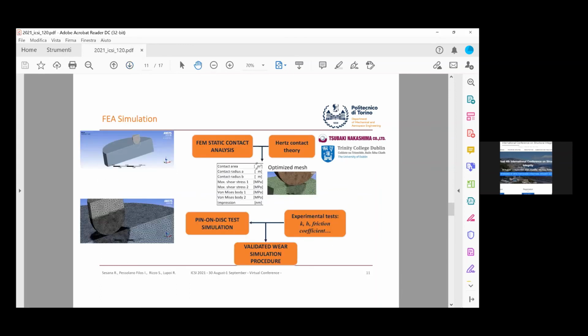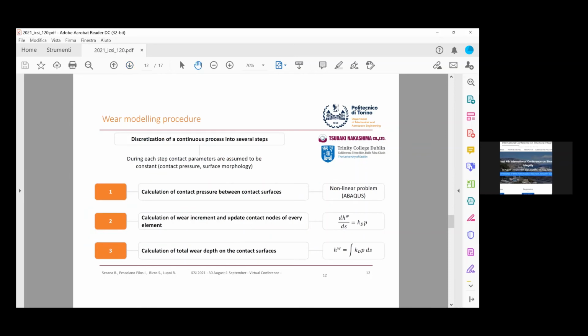After the experiment, we performed a finite element analysis on ABAQUS software. First, a static contact simulation was performed to find the reaction force needed for the second simulation, the pin on disc one. For what concerned the wear modeling procedure, the continuous process was discretized into several steps. Therefore, the contact pressure between the contact surfaces was calculated. Then the wear increment and the contact nodes of every element were updated. At the end, the total wear depth calculation on the contact surface was possible. The model assumed that during each step of contact, the parameters, such as pressure or surface morphology, are constant.